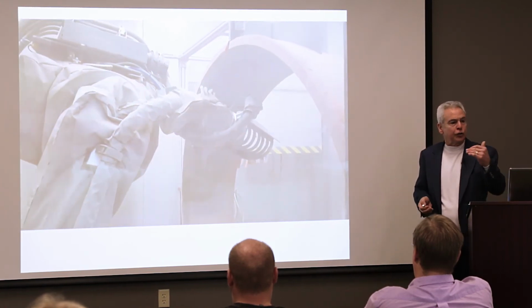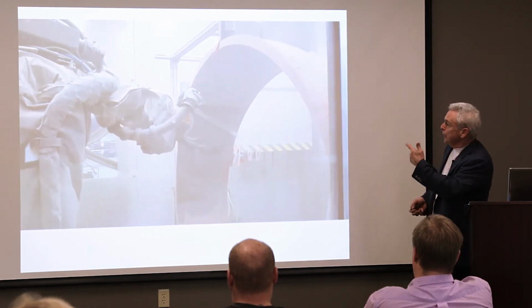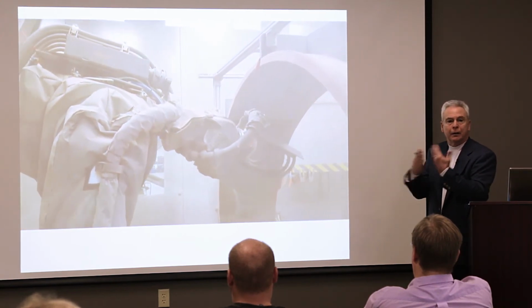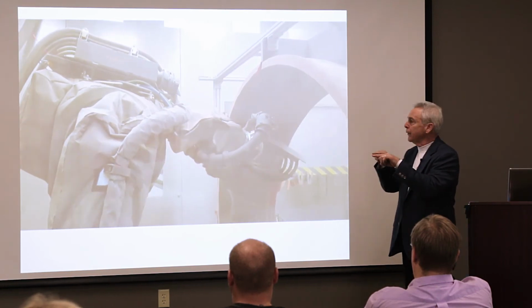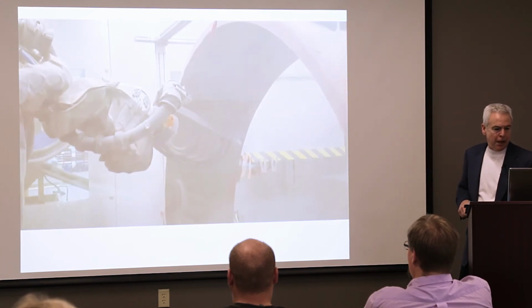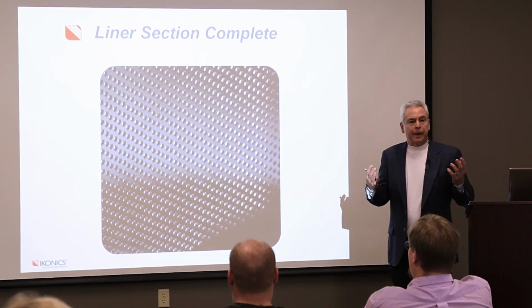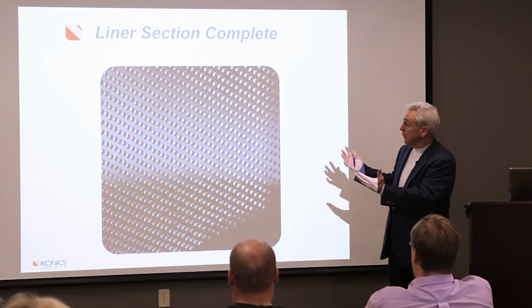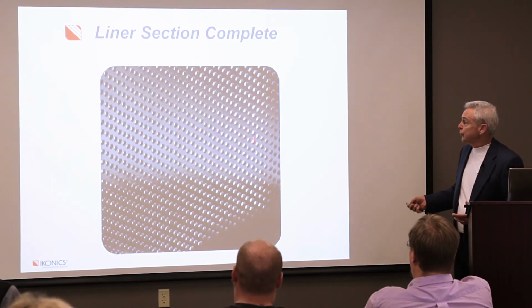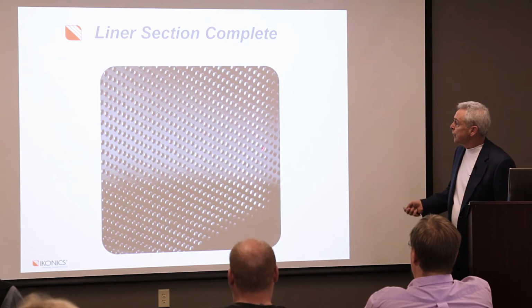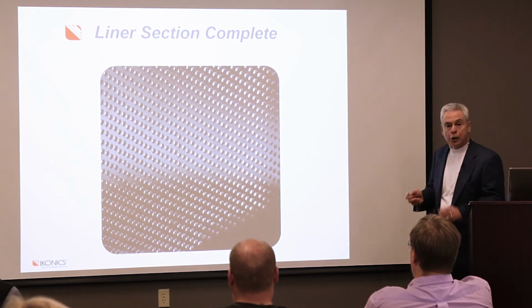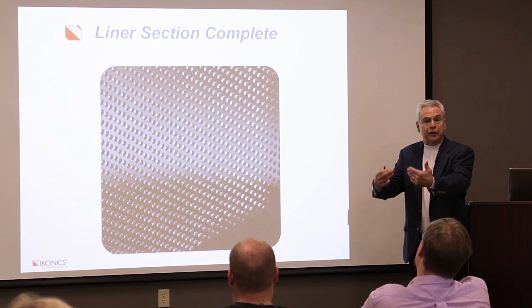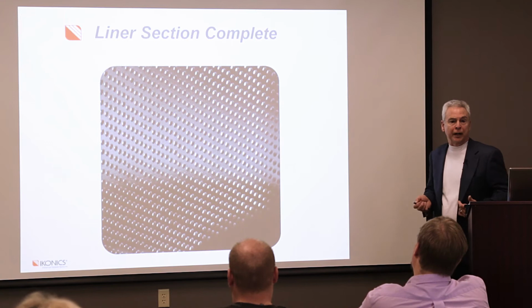Several hours later, all those holes will have been blasted very gradually, and I'll show you the process of how that works. But that's essentially what's going on here. And the mask, this photoresist that we have on here in the red, is resisting the abrasive, and it's only going through where the film was imaged. When you're done, you remove the mask, and remember the mask has protected the entire substrate during that whole process. And so what you can see here is just a section of that liner that's been removed, and you can see how uniform and clean all those holes are. No secondary processes are needed. There's no burr. No stresses have been put into the material, and it's ready for use right after blasting.